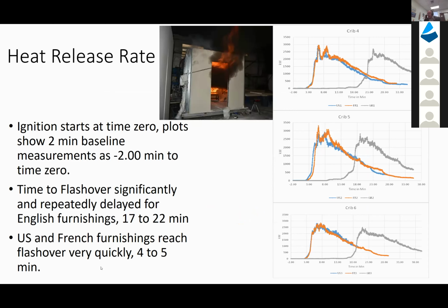So what does this look like measuring the heat release rate? You can see in the crib 4 case, 3 to 5 minutes in, you're at flashover for both the French and US room. And the same thing is true for crib 5 and 6. The time scale didn't change very much, even though more ignition energy was used. You do see a slight difference with the UK rooms, where the gray line is shown in those. It's a much later transition to flashover, but the larger the ignition source, the earlier that tends to happen. But it's still at least 17 minutes of escape time before you actually reach flashover.